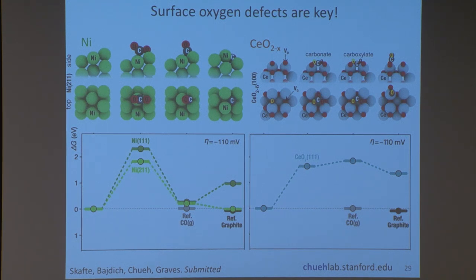So it doesn't like to deposit carbon because you have to go over here. But this is still not a desirable landscape because it's very flat. It means nothing will happen, okay? But if you start to remove oxygen, so now this is removing 1 out of 8 oxygen atoms from the surface, so now you have an oxygen deficient surface, then you have the situation where the carbonate, which is this column here, becomes much more favorable. And this makes sense because you want that CO3 2- atom to sit where the missing oxygen is in order to fulfill the better coordination.